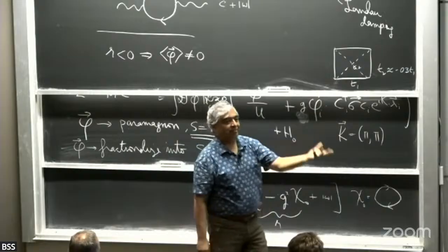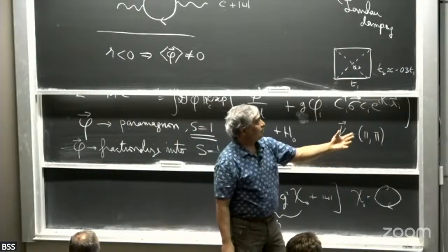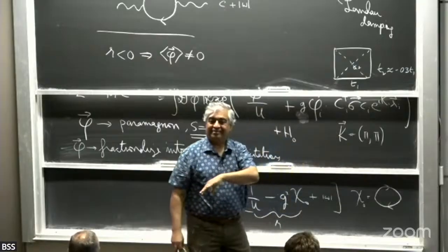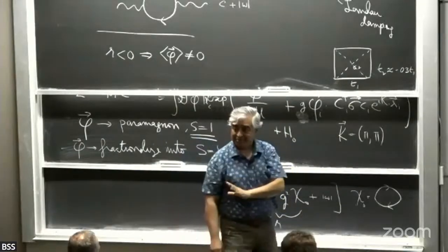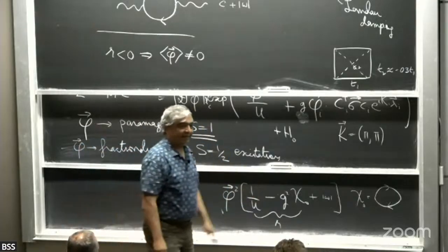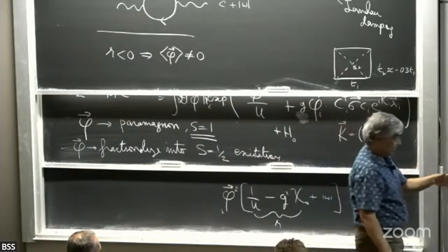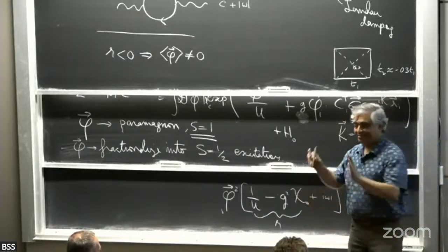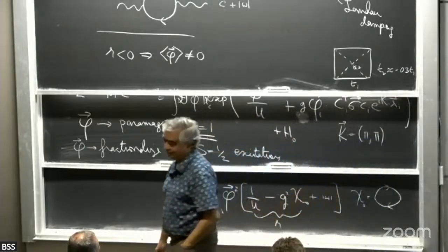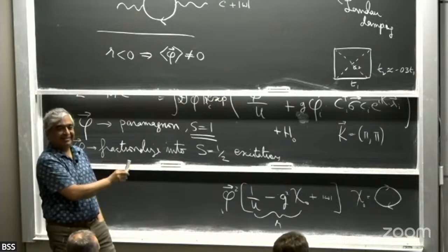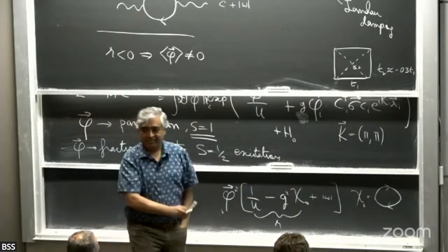If you take 1 plus x density with T2 negative, you will get 1 minus x density with T2 positive. So it maps onto a different problem. The cuprates have T2 negative, period. And that tells you that 1 plus x is different from 1 minus x. That's the biggest difference between the two. The fact that T2 is negative destroys particle-hole symmetry.